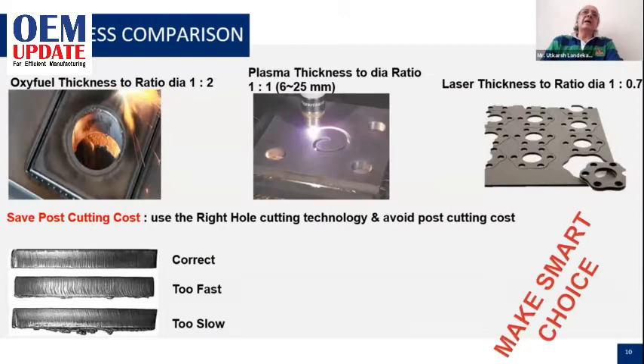Another reason for selection of the process is the hole that is going to be cut. The hole is the main reason where the types of process start getting differentiated. For laser, the reliable hole size is 0.7 times the thickness. It can go a bit lower also, but the holes are not so good. Plasma, between 6 mm and 25 millimeter in mild steel, can cut in the ratio of 1:1, and in oxyfuel it can be 2:1.